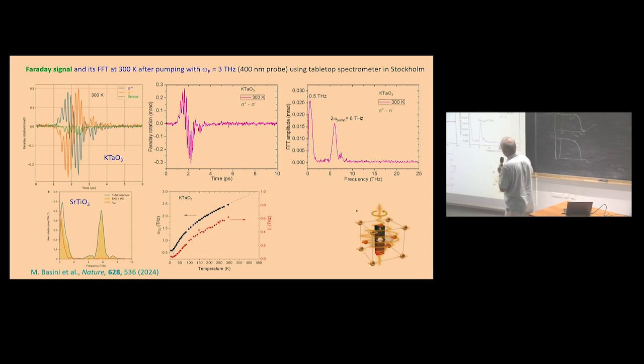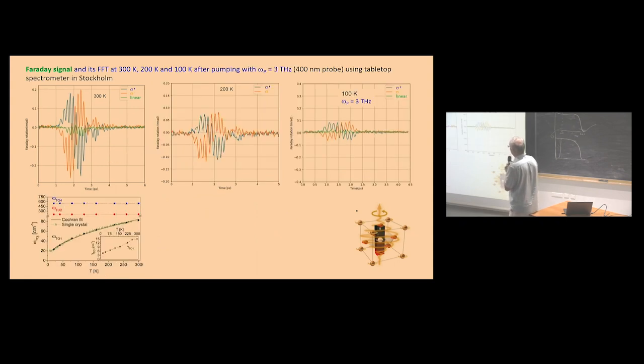This can be pumped with 3 terahertz because at room temperature the frequency of the soft phonon is already okay. At 300 Kelvin the phonon frequency should be around 2.5 terahertz. So we are close to the soft phonon frequency. And when Martina pumped this strontium titanate at different temperatures, again with 3 terahertz, you can see a decrease of the magneto-optic Kerr effect, because you are coming out of resonance, because the soft phonon at 100 Kelvin has a frequency around 1.5 terahertz. But when she heated up the sample, the intensity of both peaks is increasing, because above room temperature the soft phonon will be at 3 terahertz around 400 Kelvin. So we will come to the best resonance around 400 Kelvin.